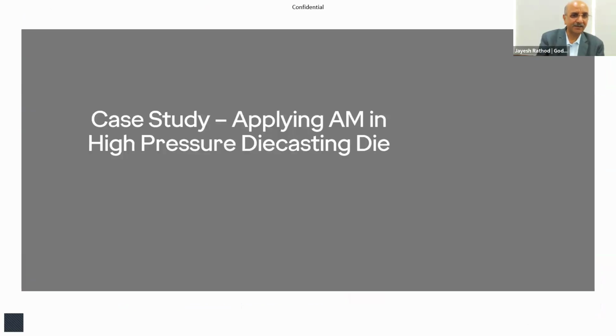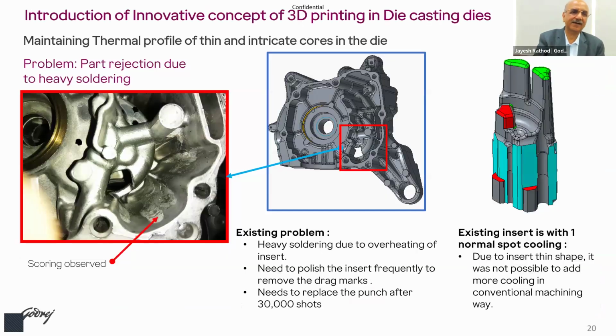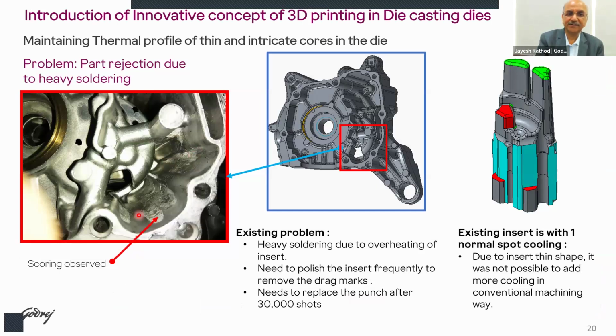Now, I will share our experience in applying additive manufacturing in a high pressure die casting die. In this die, this is a problem case where the internal profile temperature was increasing to such an extent that scoring was observed. This profile, what we see here, is formed by a local insert. Because this insert has such a thin section, we are not able to provide any cooling lines up to the top of the green area, which is highlighted here.